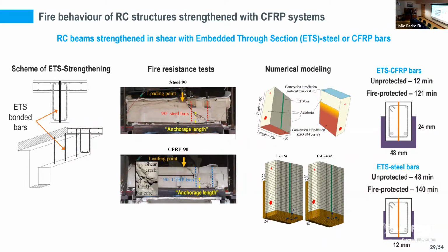And finally, we also investigated the fire behavior of RC beams strengthened in shear with the ETS method, so the embedded through-section method, where the strengthening material is bonded inside holes that are drilled at the middle of the cross section of the concrete member. For that, we developed a new test setup complemented with numerical modeling, and we concluded that when unprotected, these systems are relatively susceptible to fire. So fire resistance times are relatively low when these systems are left unprotected, but we were also able to provide some solutions to increase those fire resistances. This is only one slide summarizing this study, but this research, including the development of the test setup and the calibration of numerical models, took more than 2 years.